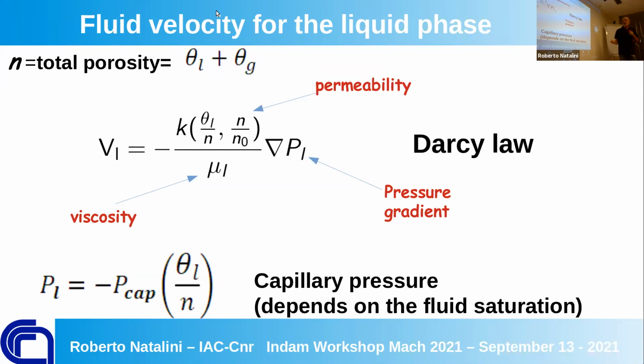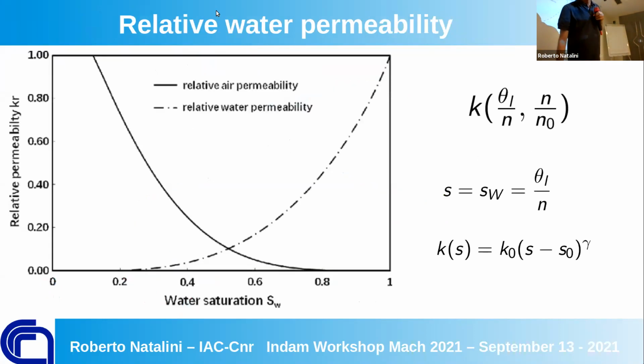And the capillary pressure depends on the fluid saturation here. Here are the curves for the relative water permeability, for instance, and also the gas permeability, the other medium. And we used some kind of loose formula, just a polynomial approximation. But the main point that you have to retain is that under a threshold, you have nothing. I mean, you have no capillary rising, so nothing happens under, for instance, 0.2, something like that. That's from the books, a classical value. So 20% of humidity inside of the pore, and then you have this growth.